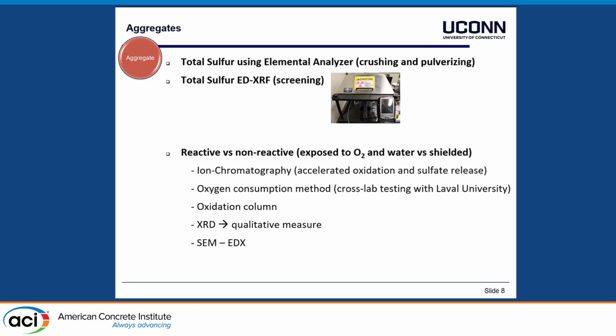And it has currently no implementation to distinguish between sulfate and sulfide sources, which you measure there. In fact, it's calibrated for the sulfate sources, so it gives you some error for the sulfide if you would use this. So that's why it's only a screening tool. In terms of looking at aggregates, how reactive they are.